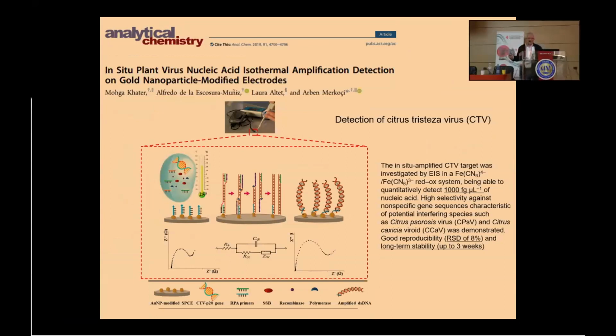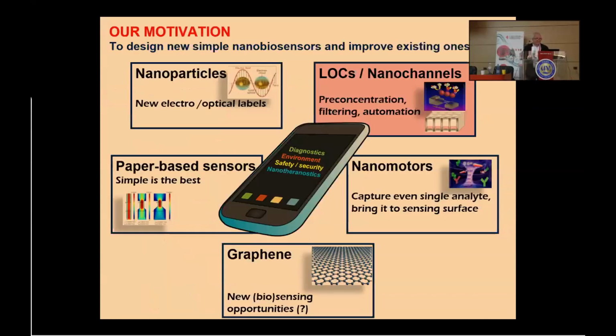So this is something very, very interesting because it allows you to apply a PCR system that may be also of interest for COVID. In this case, we applied this to detect some plant virus-related nucleic acid. But in principle, you can work for different applications, just by changing the sequences of DNA. And we measure this by using impedance spectroscopy, which is a very interesting electrochemical technique that measures the interface between the electrode and the components you want to detect.